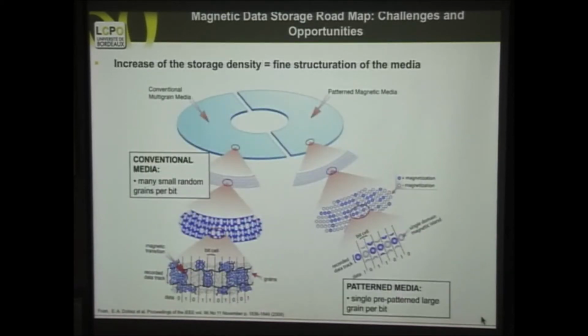Patterned media, what are they? Well, here is the story. Here I have a disk with today's technology, where you have the tracks and the bits that are written in every track. And you can see that for every bit, you have many magnetic microdomains. However, if you go to patterned media, every single particle can be 5 or 10 nanometers big, provided that it's not superparamagnetic or paramagnetic; you have to respect the rules of the materials for that. So then you can have 1 bit per particle.